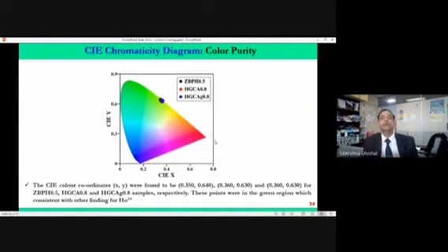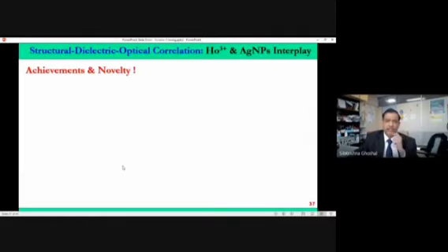But the last thing we want to check is, what is the purity of this color? We have wide green, because we know in the visible spectrum, green can be several wavelengths. Red can be several wavelengths. Yellow can be several wavelengths. But which red wavelength? Which green wavelength? That means the monochromaticity and color purity can only be checked by the chromaticity diagram. This is called the CIE chromaticity diagram, and these are the coordinates for the chromaticity. When we check, we see the color purity for red and green is quite interesting, and that's what we wanted, and we achieved the target for the time being.